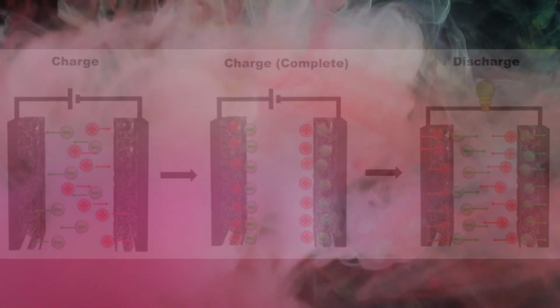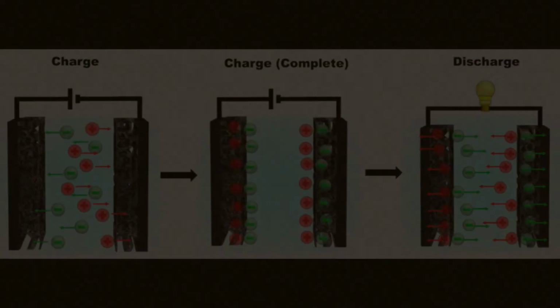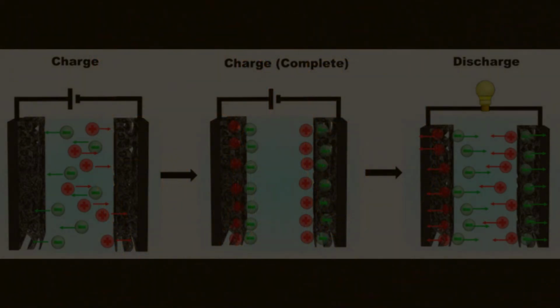By combining the networked metal sulfide nanoflakes with reduced graphene oxide, RGO, nanosheets, the resultant material would be able to flex to the shape of any arbitrary solid-state hybrid supercapacitor. The films yield a high specific capacitance of 1739 farads per 1 gram at a current density of 0.5 ampere per 1 gram. This fabrication process can feasibly prepare fully printable supercapacitors and other electronic devices at a large scale, holding immense potential for the personalized technology field.